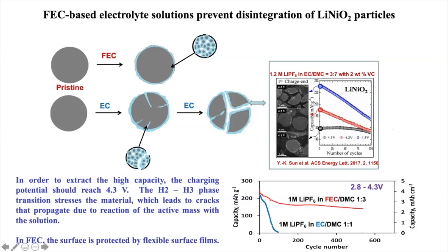Going further, here we can demonstrate the mechanism. What happens, in fact, is that we have cracks in the material, and when these cracks reach the surface, we have a penetration of solution inside. So we have exfoliation type reactions, and propagation of the cracks. They start with stress, but they continue to propagate with reactions with electrolyte solutions. And now we can get a complete disintegration of the material in certain cases.